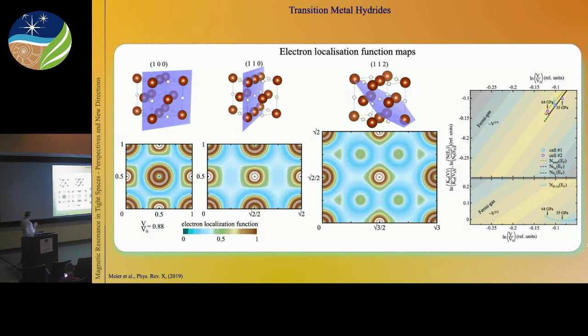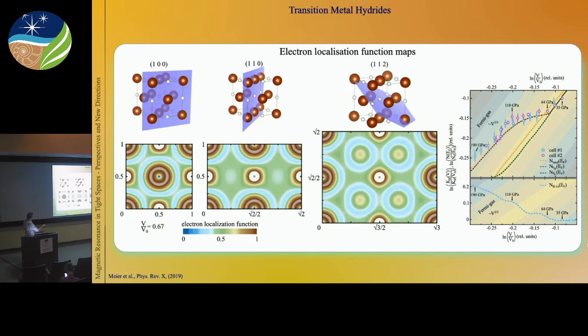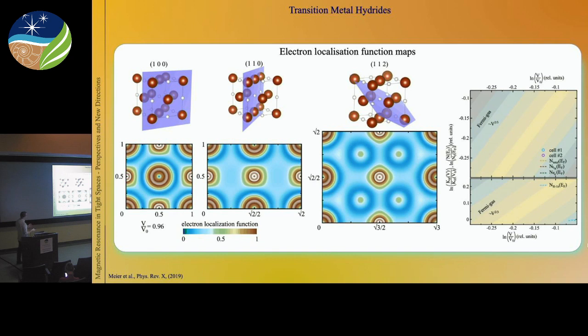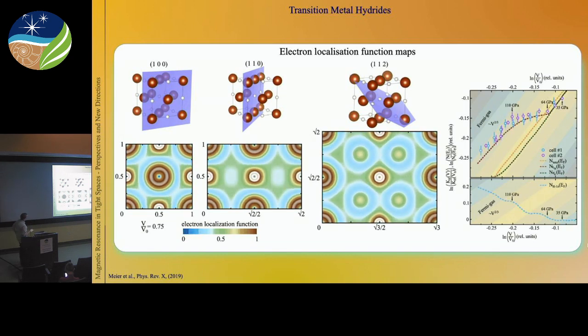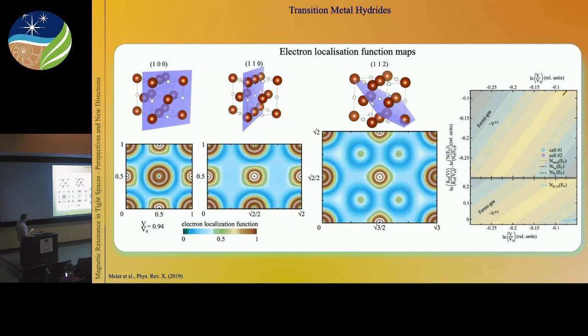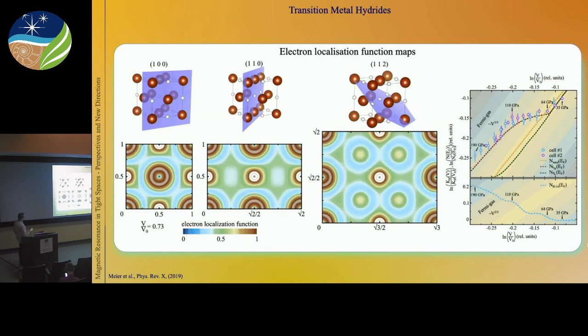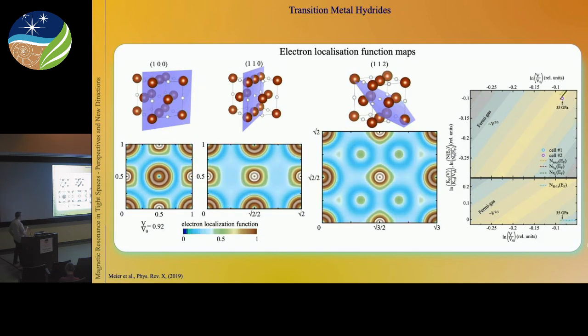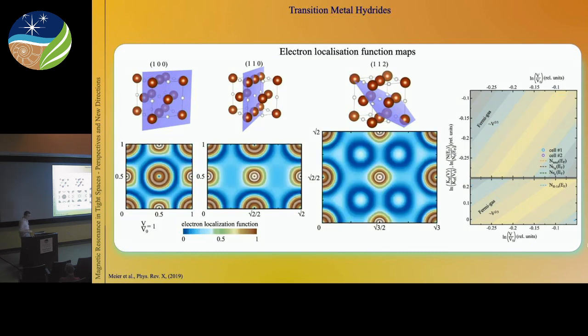And these pockets are actually combining towards an intercalating sublattice of free electron gas, combining all of the hydrogen atoms in our crystal structure. After seeing that, we realized that that might even be the formation of that metallic hydrogen sublattice, which is anticipated in metal hydrides, which is actually thought to be the driving force of this high temperature superconductivity we see, for example, in superhydrides.